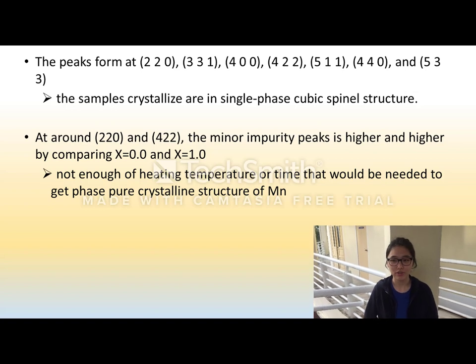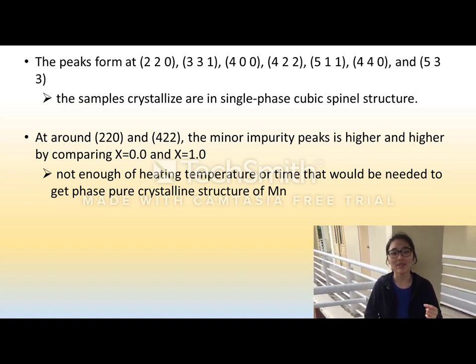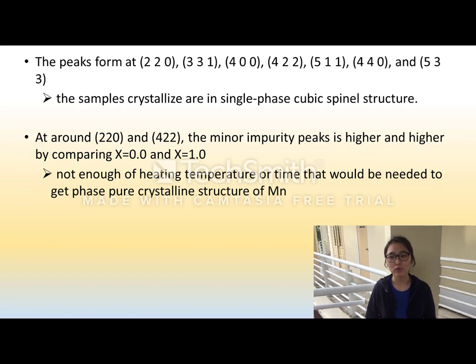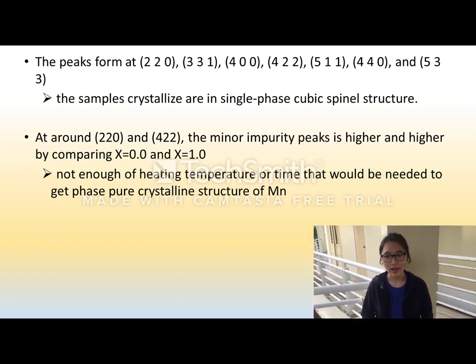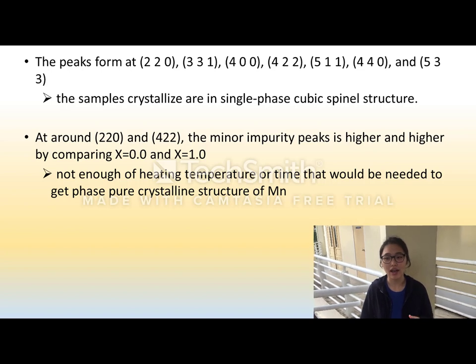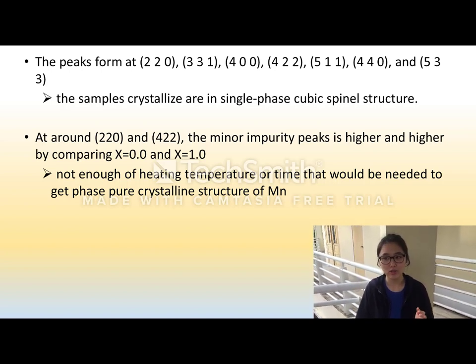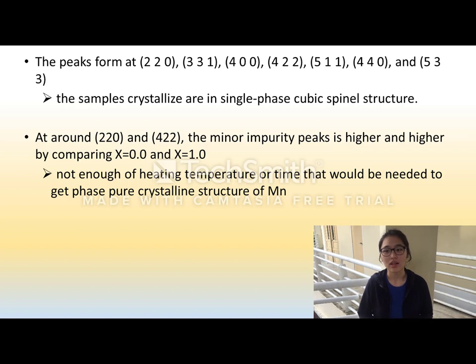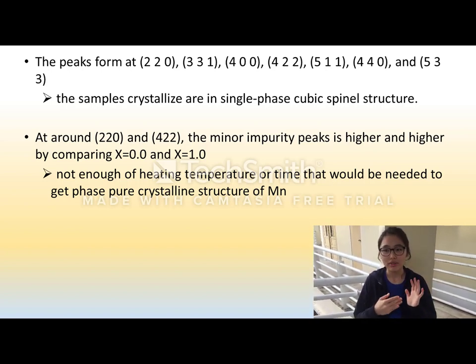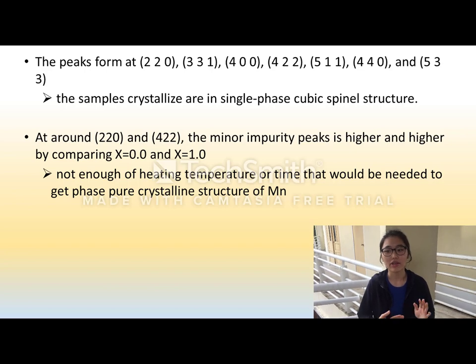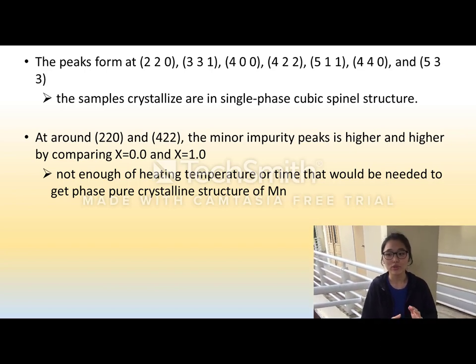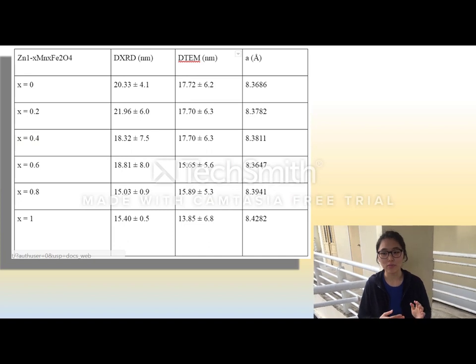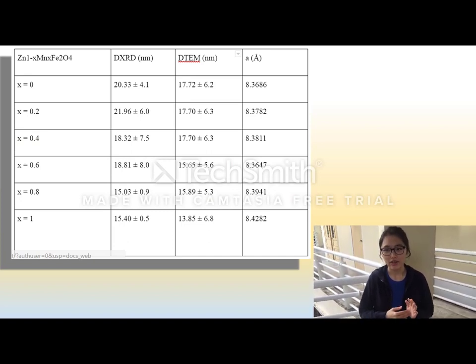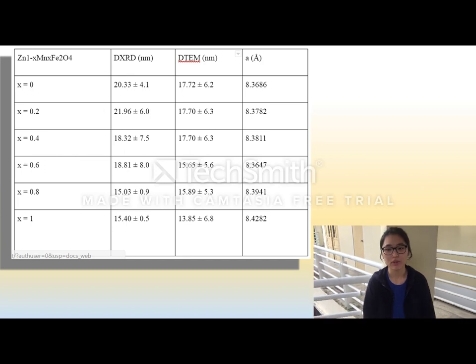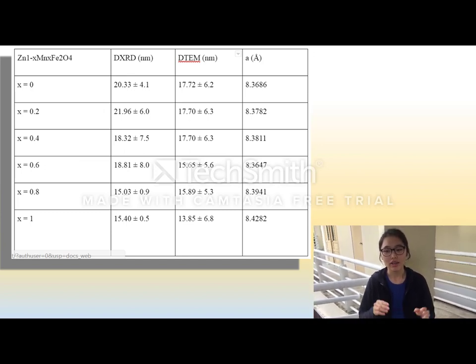cubic spinel structure. Other than that, at around 220 and 422, there is a minor impurity peak, and the peak is getting higher and higher by comparing x equal to 0 and x equal to 1. This is due to not enough heating temperature or time needed to get a phase pure crystalline structure of manganese substituted zinc ferrite. In the next table, the XRD and TEM sizes decrease by increasing the content of manganese. On the other hand, the lattice parameter is increased.